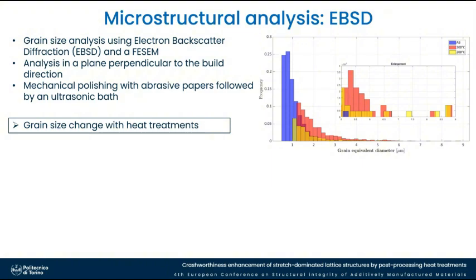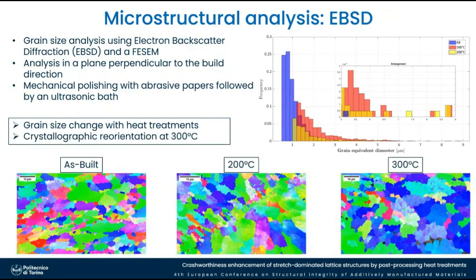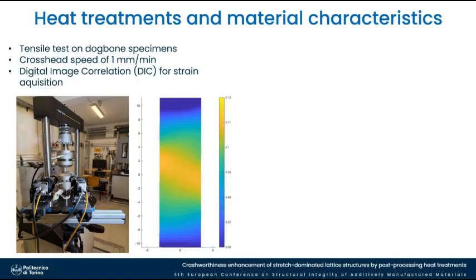And also, we observed with these color maps that the grain size increases with the temperature, but also that there is a crystallographic reorientation of the grains. So all the grains assume more or less the same colors, that is, they have the same orientation. And this change in the grain size is in accordance with the more rounded shape that we've seen with the micro-CT, I would say.